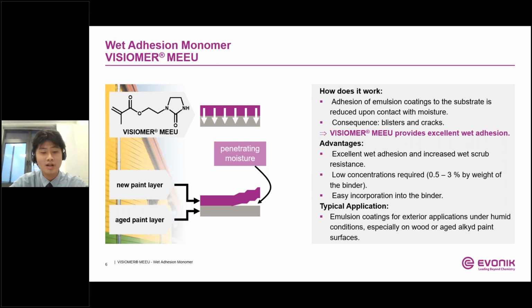Meanwhile, only low concentrations are required, 0.5 to 3% by weight of the binder, and it does not bring problems in the reaction, which means it easily incorporates into the binders. One of its typical applications is as a synthesis component in emulsion ester coatings to improve adhesion under humid conditions, especially on wood or aged alkyd paint surfaces.